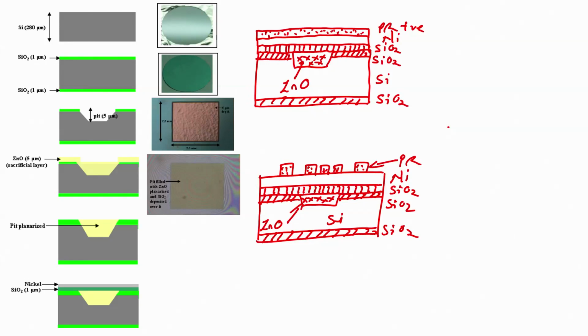After that, what will you do? Next step is to etch nickel, right. So, where will nickel get etched? Nickel will get etched in the area which is not protected by photoresist. So, this is what we will have. Nickel which is not protected by photoresist will get etched, and nickel which is protected by photoresist will stay, right. After that, what is the next step? Acetone dip, right. When we dip the wafer in acetone, what will happen?